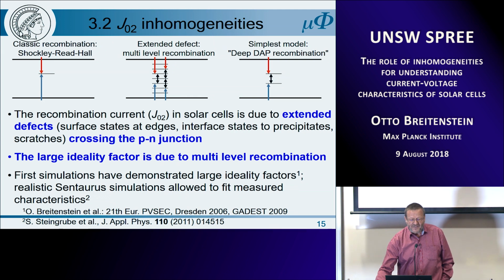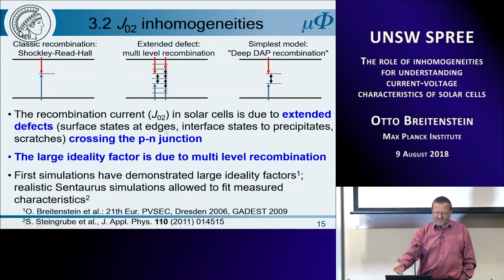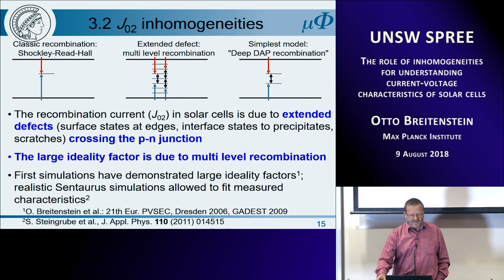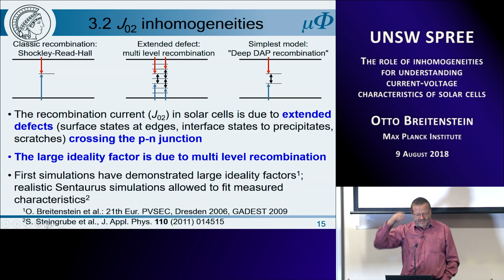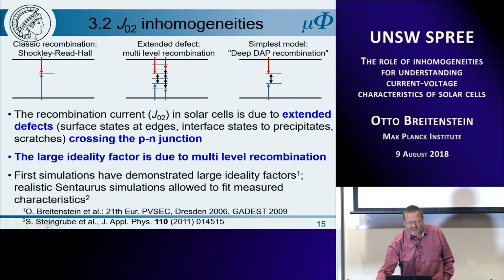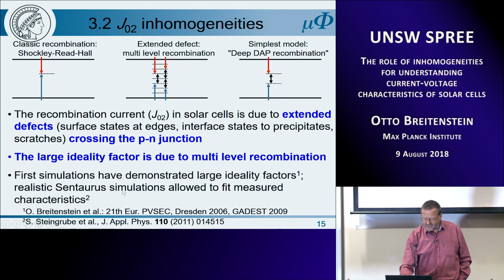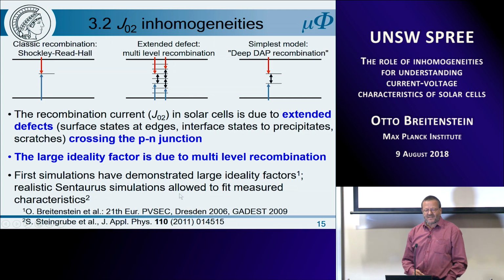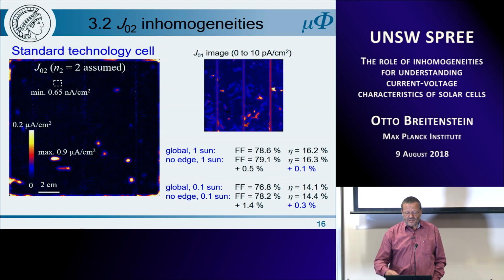So if we have extended defects, which may be surface states at the edges, or interface states to precipitates, or scratches, as I've shown, crossing the pn-junction, then we can expect multi-level recombination. First simulations have shown this already in 2006. And now Silke Steingrube, who was a PhD student of Pietro Altermatt, has realistically simulated this and managed to fit measured characteristics with this model. So we think that we understand this now, and let us show the influence.